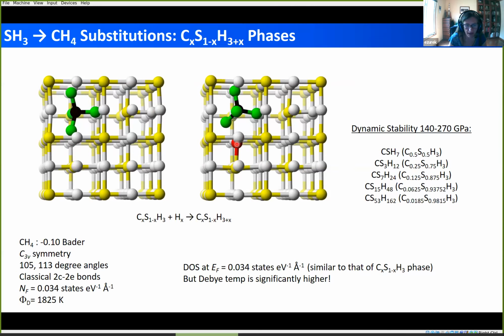Note that it does not have much of an impact on the DOS at the Fermi level. However, what it does have an impact on is the dynamic stability range. So these types of substitutions are going to be stable along a much larger stoichiometry and pressure range.